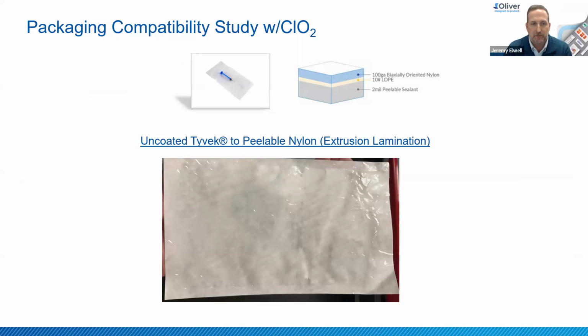The one area that we talked about before with film delamination did come up in this study, and it really was expected. In this situation, this was when the chlorine dioxide chamber had the vacuum added to it. And so it really exemplified and amplified this issue that we sometimes see. So this was expected, but with some extrusion laminations, this film delamination can occur. The picture below shows the wrinkling or those lines throughout. That's those two layers of film separating from each other due to the failure of the primer in between. And in that structure, the primer is not shown, but the nylon and the LDPE layers are separating from each other after exposure to chlorine dioxide. So this doesn't happen in every situation, just with certain materials that are extrusion lamination and in that vacuum type environment that we've seen so far.